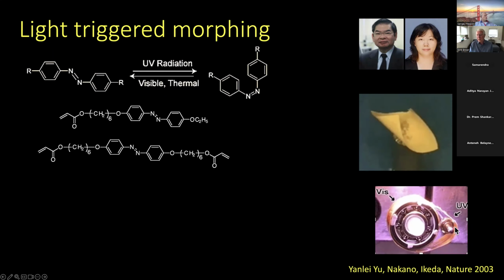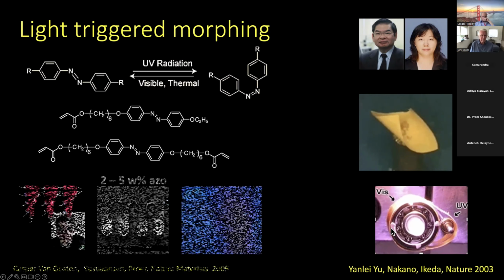They also created already a kind of motor system. I'm always jealous about this device. They make a belt of this material, they expose it with UV light here. The film builds up some stresses because it wants to bend, and it can, so it starts to, and it can release the stresses just by rotating. And you can bring it back to the trans state isomer by exposing it with visible light.